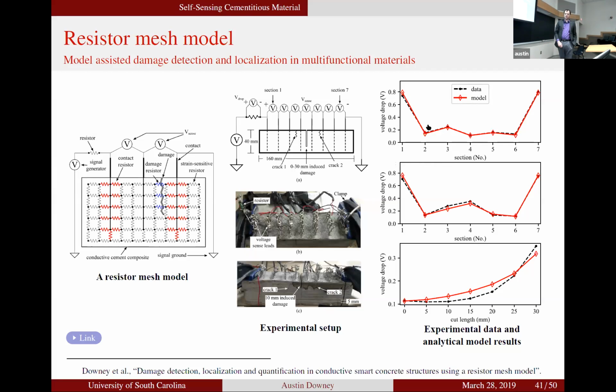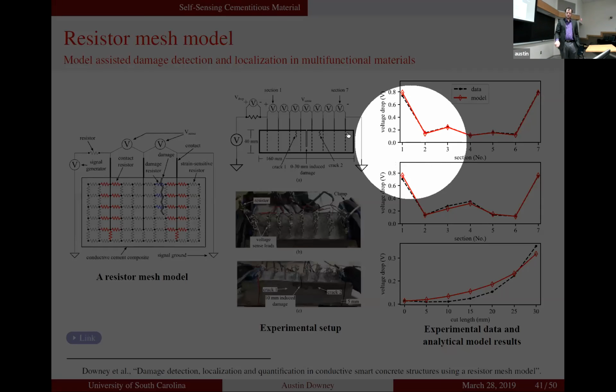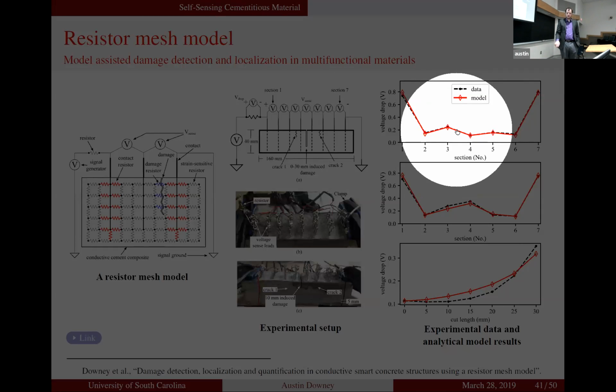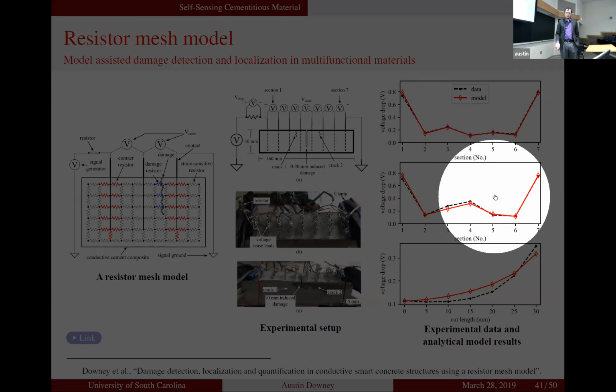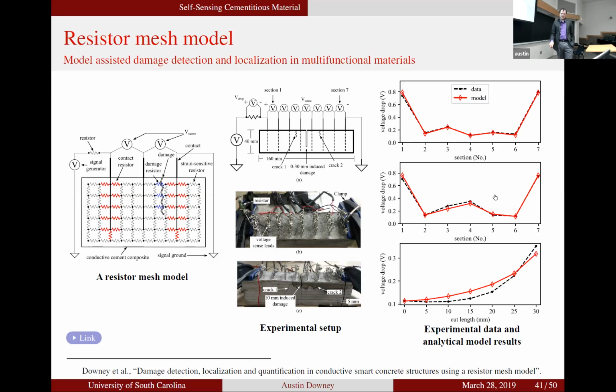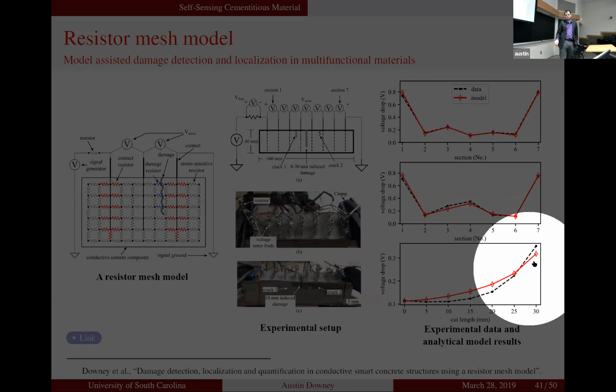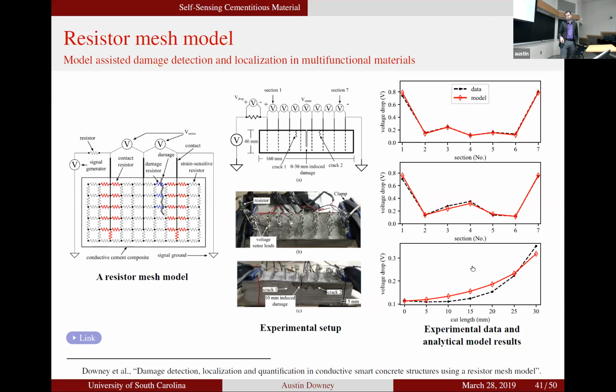And so the data line is what we get with what we're actually measuring. And then by adjusting the value of the damage around our cracks, right? So we have 2 cracks here, 1 and 2. We can adjust our model to match the data pretty well. And so here we have adding crack depths to it, and then with the increase in crack depth, so we're just sawing through it, our model is able to track it. And that video is not gonna work. Okay.